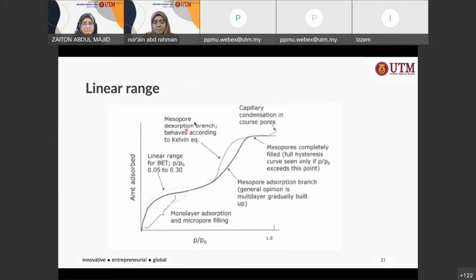Okay, so this is just a bit of description of the isotherm. This is the linear range, and this is the monolayer adsorption which is being covered here. We do not take other ranges of P over P naught; we only take between 0.05 and 0.3. Of course, the micropore filling also takes place here. So if your sample has micropores, you have to be a bit cautious when you determine the BET surface area.